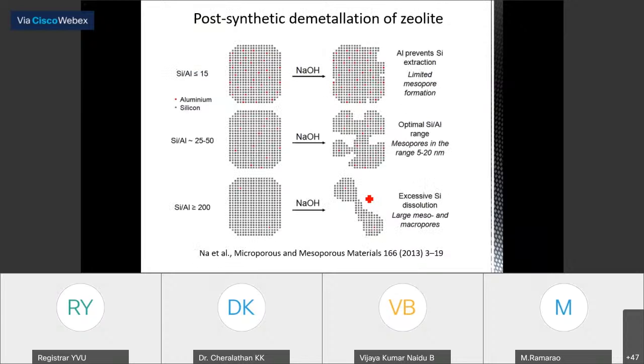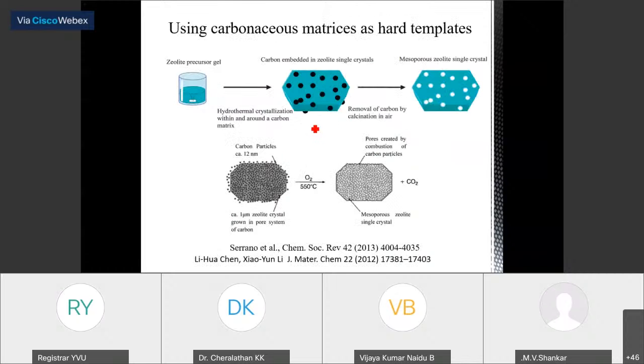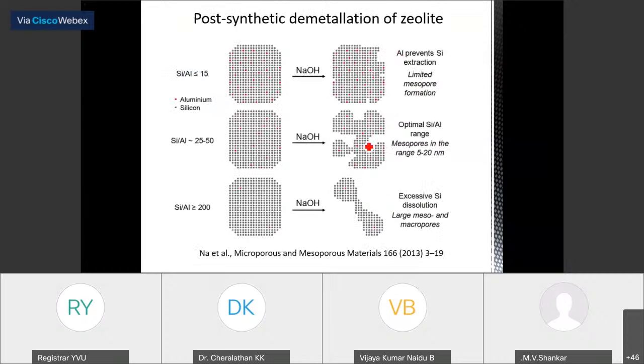This is possible. Not only that, even you can remove some of the silicon and aluminum present in the zeolite by reacting it with an acid or alkali. Here, post-synthetic desilication of the zeolite is shown. So it is made up of silica, isn't it? It is having silicon and aluminum. So when you treat the zeolite with sodium hydroxide, what will happen? The silica will dissolve. So if you control the conditions, what will happen? You will have the zeolite with this kind of additional pores created. So this is post-synthetic demetallation. The previous things, during the synthesis, you are introducing something and removing. Here, after the synthesis of zeolite, you are removing some silica and alumina to get the mesoporous material.